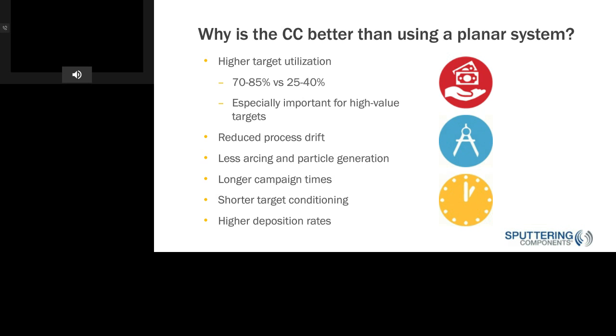There's reduced process drift. The stronger magnetic field design in a rotary cathode and a narrower design too compared to a planar cathode lowers the impedance and lowers the process drift. You also get less arcing and particle generation, simply because the target is moving all the time, so it's staying clean, so it doesn't arc as much. For rotary cathodes, there are 3 to 4 times the material available compared to planar cathodes, so you get much longer campaign times just purely because of the amount of material.